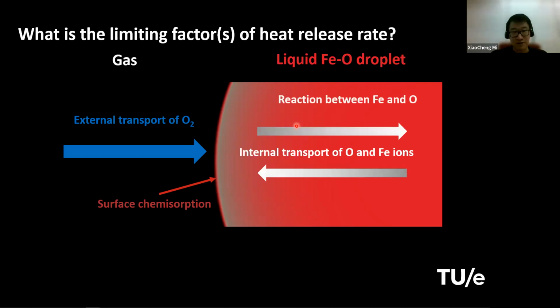And another thing, which is actually not very likely rate controlling, is the reaction rate between your Fe and O ions. Why I'm saying this is not very likely the case is because at this very high temperature, once the oxygen has dissociated into the particle as ions, it can react with the iron atoms very quickly. There's almost no activation energy required for this reaction to happen. So the reaction rate itself might not be the rate limiting factor because it's very rapid.